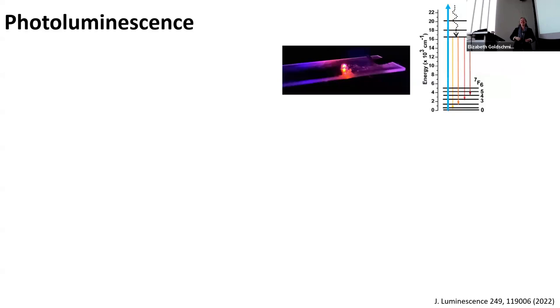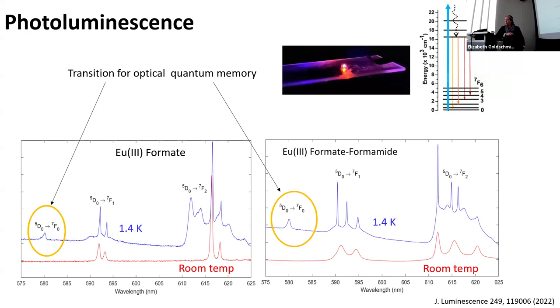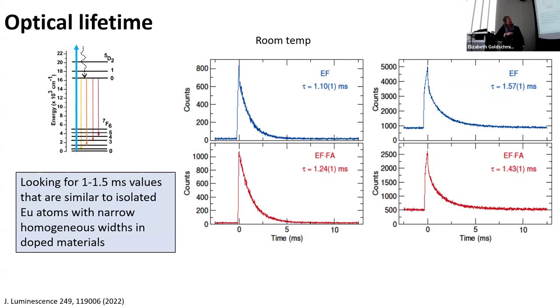It's fun. And so we look at what comes out, and we can see the transition of interest for quantum memory is this one that doesn't always appear for symmetry reasons. So we want to see it in our photoluminescence. We can do optical lifetime measurements and see that we have this standard 1.5-ish millisecond long lifetime at cryogenic temperatures. We haven't measured the actual homogeneous line width or the individual atom line widths, but this is suggestive that it's going to be reasonable.